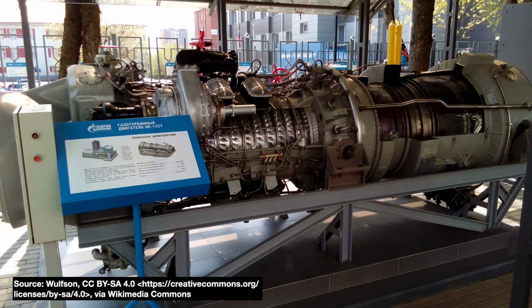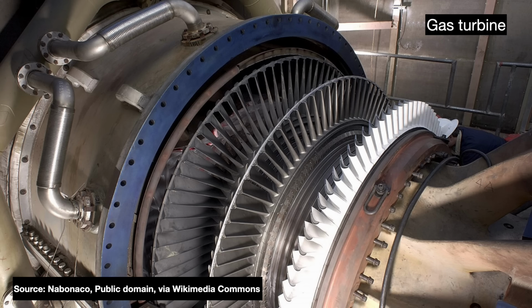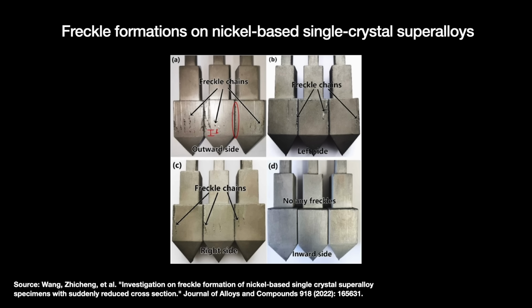Then, in the 1970s, the oil crises accelerated the advancement of gas turbines. But gas turbines require much larger blades, anywhere from 45 to 80 centimeters long. Trying to cast such massive blades exacerbated a persistent defect condition called freckling. Freckles refer to tiny equiaxed grains that form inside the single crystal. Since they are random grains with grain boundaries, they hurt the blade's strength.